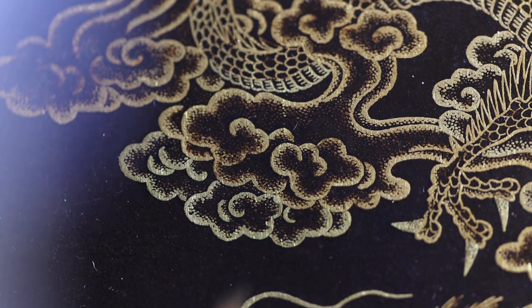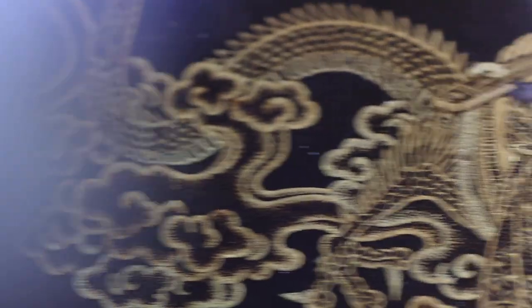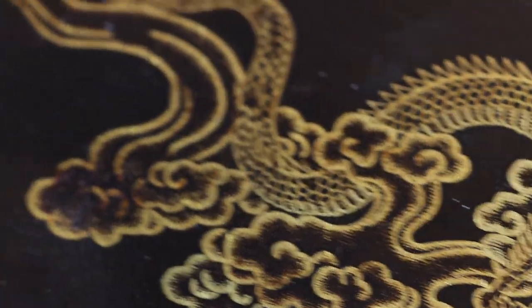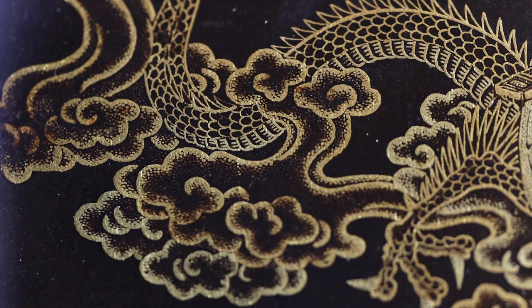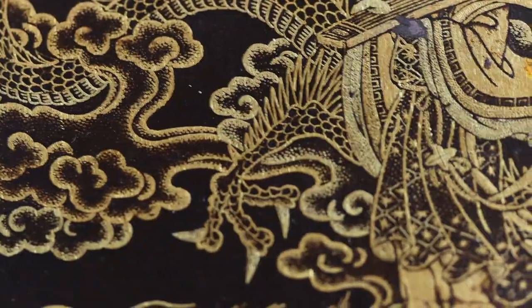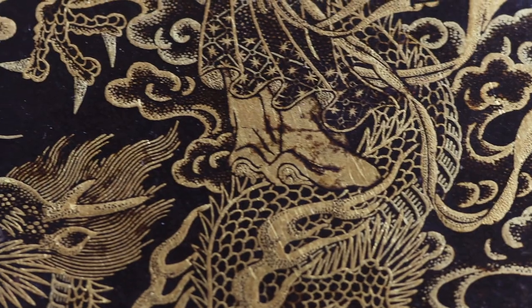So I'm going to have to do some very careful investigation into the surface. Some areas have been quite worn and I can see the metal surface fairly well. Other areas look like they've got a sort of thick varnish, lacquer or waxy type coating. So I'm going to be like a painting restorer and use various solvents in an inconspicuous area to see what is coating everything.